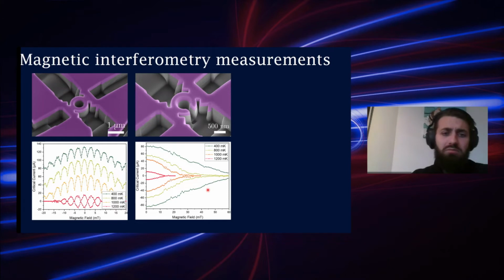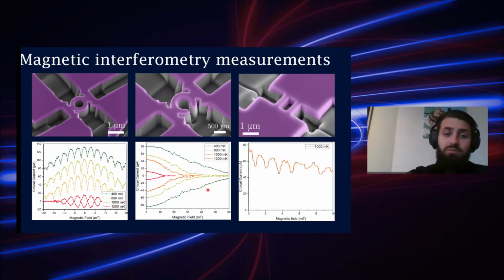And you could say maybe this is an effect caused by the geometry. However, when we simply make a doubly connected sample, what we find is still the squid oscillations that we see in the ring.